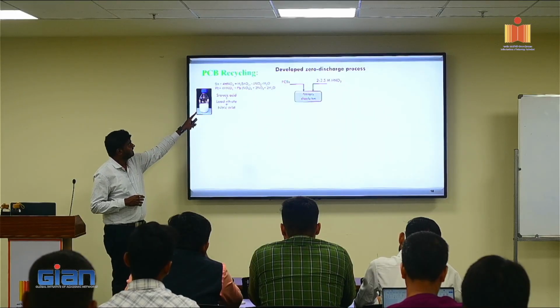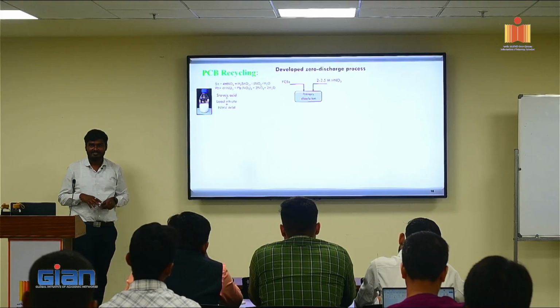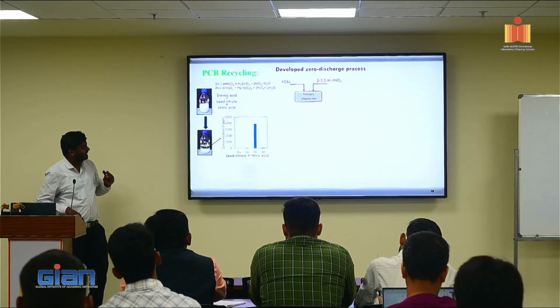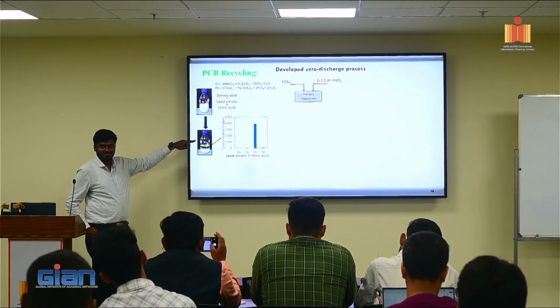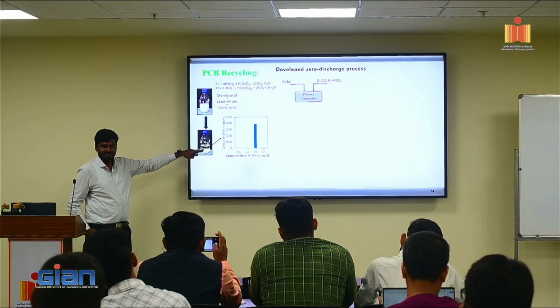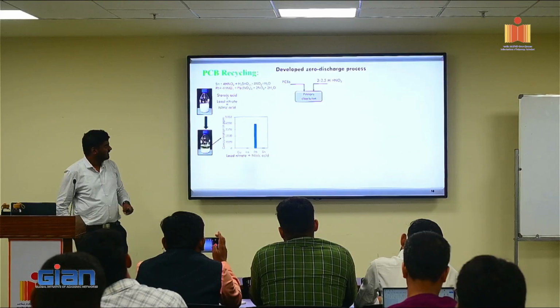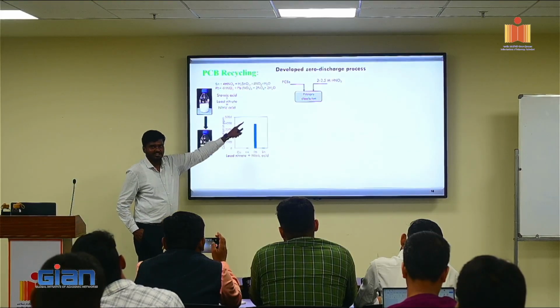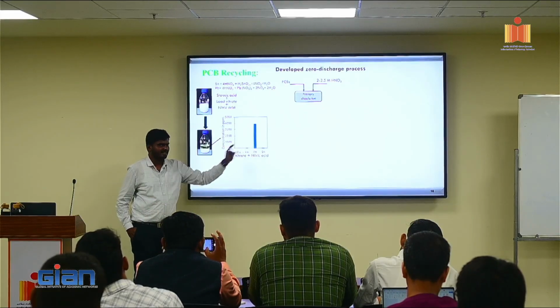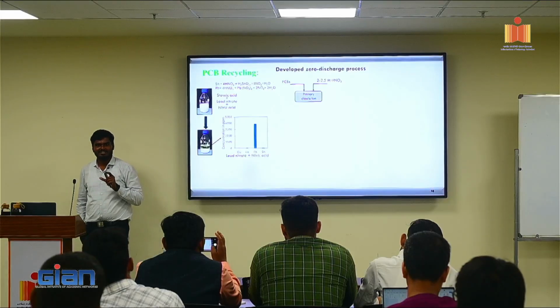Now I got this colloidal solution where tin oxide is there, lead nitrate is there, and unreacted nitric acid is there. Now I have to separate one at a time. When I leave it for some time, it took almost 24 hours, all the colloidal particles got settled down and there's a top solution. When I do ICP-OES or AAS analysis of this top solution, it has a significant quantity of only lead and very minute traces, less than 10 ppm, of copper, iron and tin. That says the solution contains only lead nitrate and nitric acid.